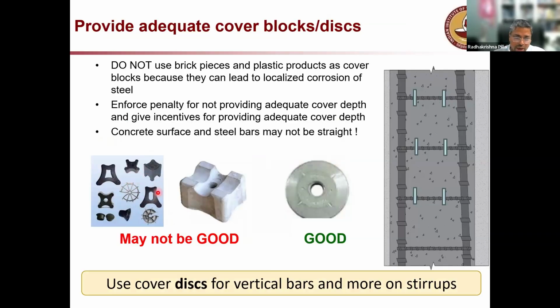Because when the concrete starts shrinking, it might open up where the plastic is, and then you have a direct pathway from outside towards the steel through which water, oxygen, etc. can penetrate. And the other thing is there are cover blocks in the market which have a very smooth surface, so you may not have proper bonding with the surrounding concrete. Cover has to bond well with the surrounding concrete. That is why even plastic may not be very good.